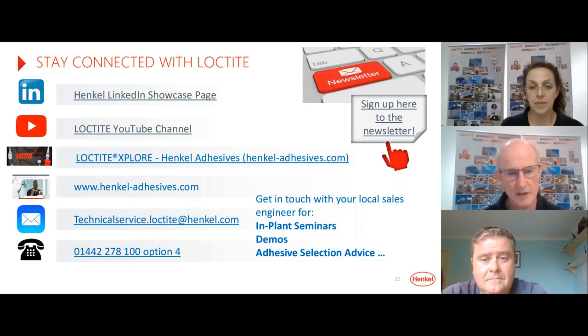But as Julie mentioned, with epoxies, for example, a slow curing epoxy is generally beneficial from a durability point of view. So it's always going to be a balance. But in most applications, the adhesive will gain some sort of handling strength within anything between a few minutes up to a few hours, and then full strength in between 24 and 72 hours. So again, it depends on the application and the type of adhesive. The polyurethanes, for example, some will cure in a few minutes and some in a few hours. So it really depends on the application.